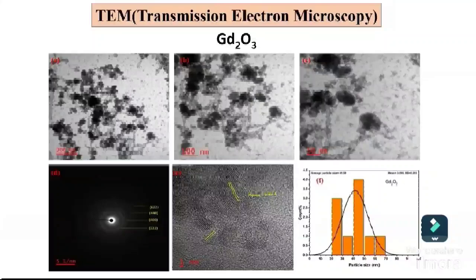So basically, this is the data for transmission electron microscopy, which shows that our particle has a pseudospherical shape, and the average size of pure gadolinium oxide is 41.58 nanometers. This is the data for pure gadolinium oxide.